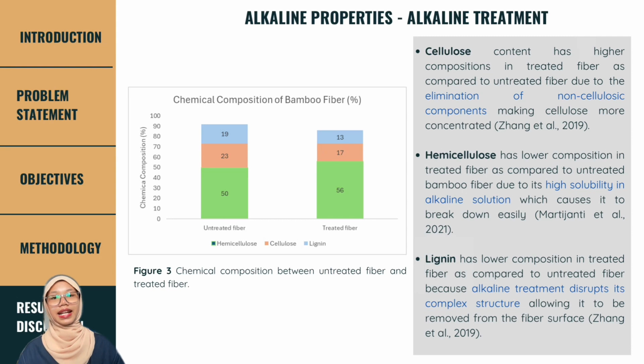The cellulose content has a higher composition in the treated fiber as compared to the untreated fiber, due to the elimination of non-cellulosic components, so cellulose becomes more concentrated, while hemicellulose has the lowest composition in the treated fiber as compared to the untreated one, due to its high solubility in alkaline solution, which causes it to break down easily.